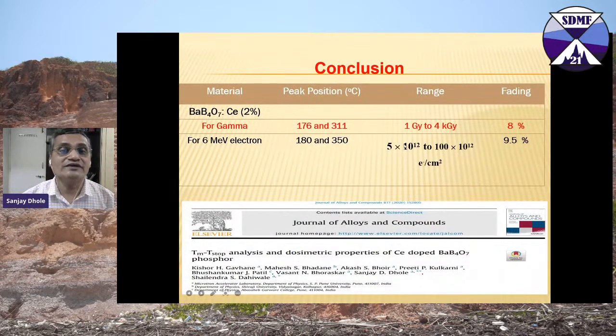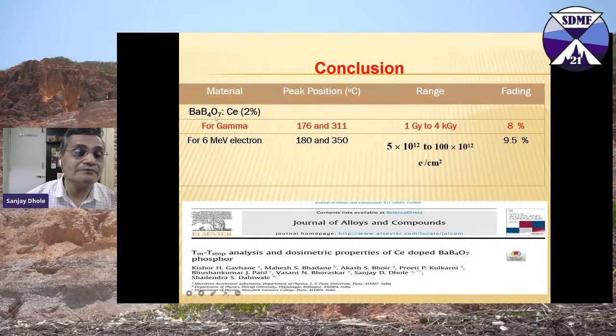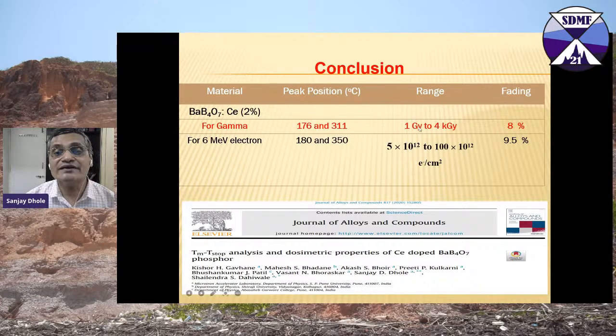So this is the conclusion in the barium borate doped with cerium with 2% for gamma. It gives 1 gray to 4 kilo gray, and the fading is 8%. This is a fantastic result which we could obtain.